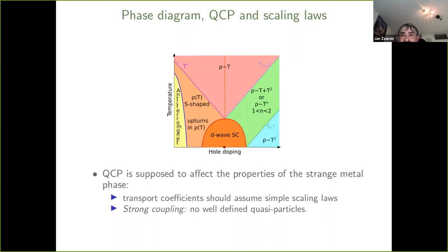Anything that looks like a diverging mass is all based on these quantum oscillations that you find at extremely low temperature, deep in the superconducting phase, in very large magnetic fields. And we know that when you get into the superconductor, you restore quasiparticles. So there's really no sign of a specific heat divergence when you look at the specific heat at higher temperatures. That's all mythology. So you're saying the log divergence that he... That's just nonsense. It's related to being at 0.5 Kelvin in a field of 60 Tesla, deep in the vortex fluid, right? We know it. That's been very uneasy all along.